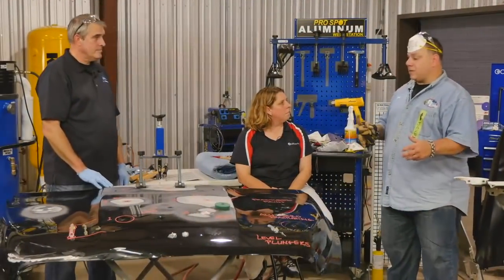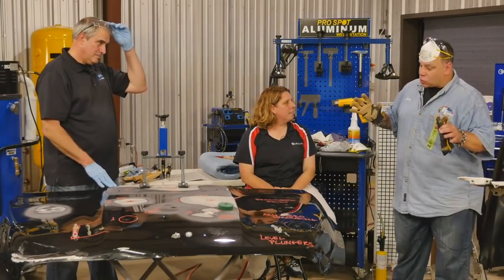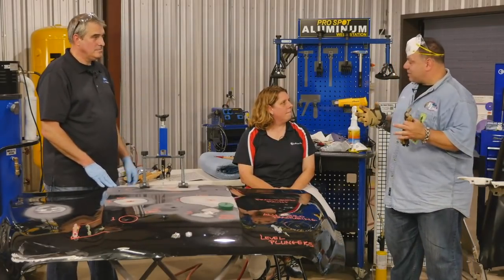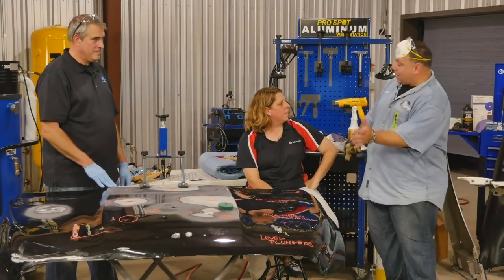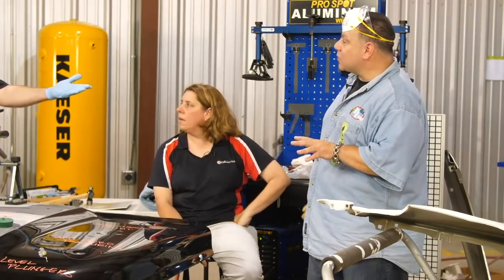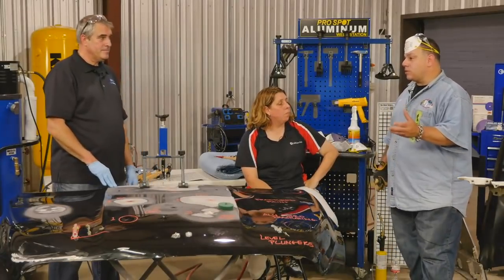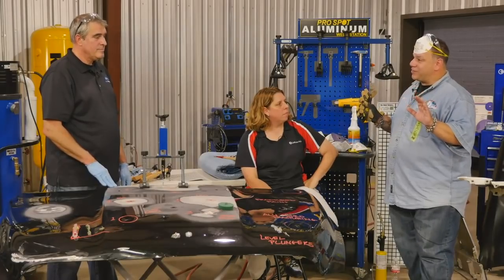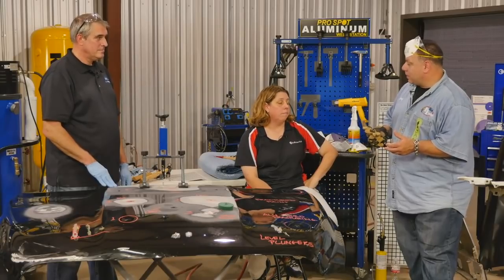You really have to take a look at the backside of the panel to see what's there. If you can use paintless dent repair techniques, great. Next, try your glue-on tab removers, great. Can I hammer and dolly? Hammer and dolly you can, but the problem is — going back to classes on metal shaping — if you do hammer-on, you're stretching and thinning out the metal. That's a beginning body technician's biggest mistake. Hammer-on is where you've got the dolly and you're hitting the metal on top of the dolly — what happens is you're thinning the metal out. What you want to do is use hammer-off, even on steel, where you push up on the damage with your dolly and bump around the outside with the hammer to get the panel flatter and stress-relieve it at the same time.